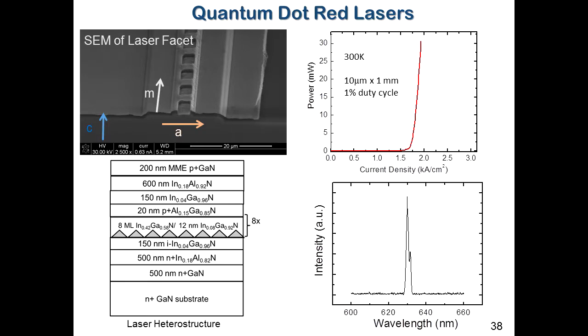The most important thing here is the threshold current density. Even in blue and green, the current nitride-based lasers made in the industry have threshold currents which are 10 times this. And with quantum dots, we brought it down to about 1.7 kiloamps per centimeter square, which for the nitride system is very, very good. Because inherently, because of the high effective masses and the density of states and so on, you know that the threshold current density is going to be large, but this is incredibly low in that context.